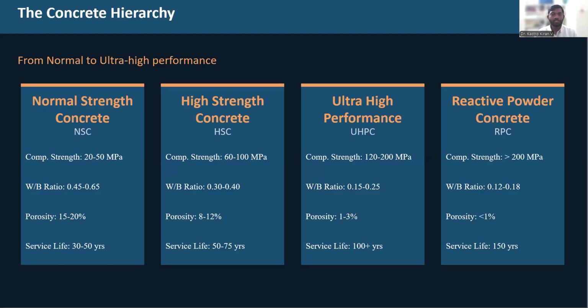In general, any normal strength concrete refers to strength between 20 to 50 megapascals, which has a water cement ratio ranging between 0.45 to 0.65. Usually this normal strength concrete has a higher amount of pores. That is why it leads to most of the deterioration characteristics and vulnerability prone areas. To overcome that, we have high strength concrete, where we attain strength up to 100 megapascals by minimizing the void content and also the water binder ratio.